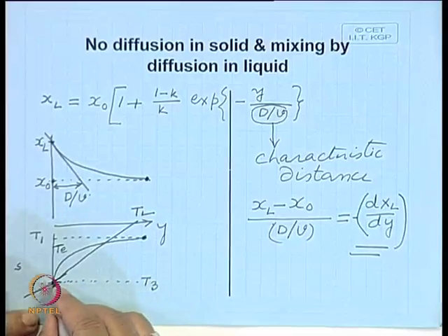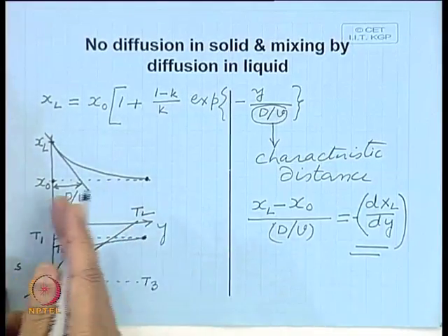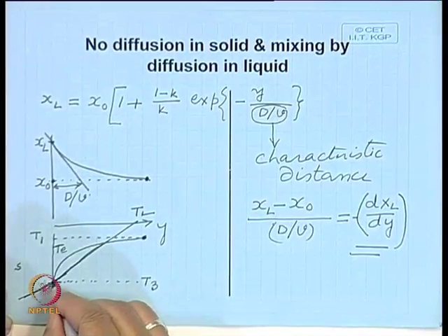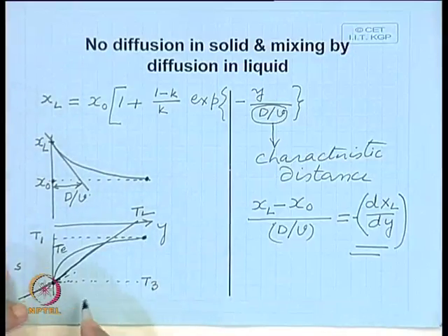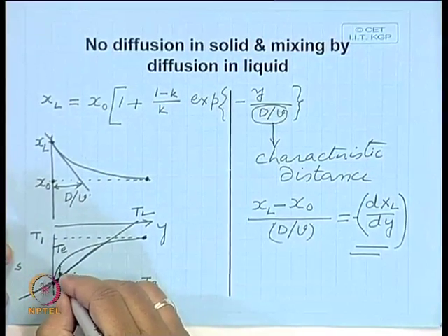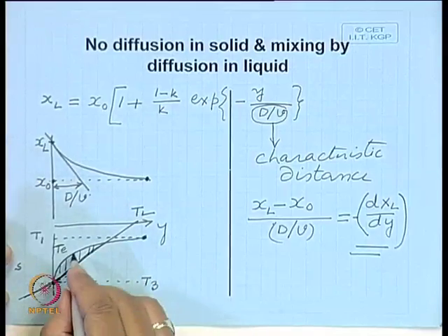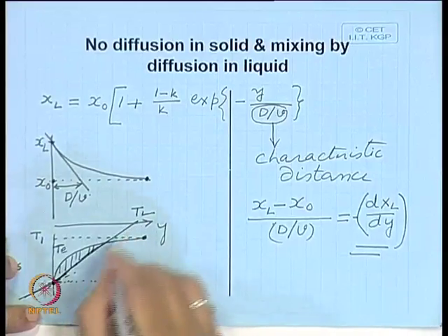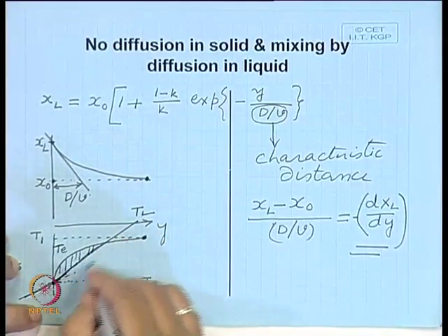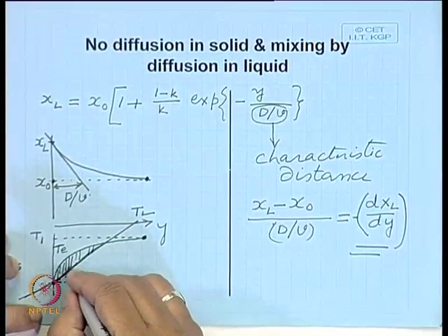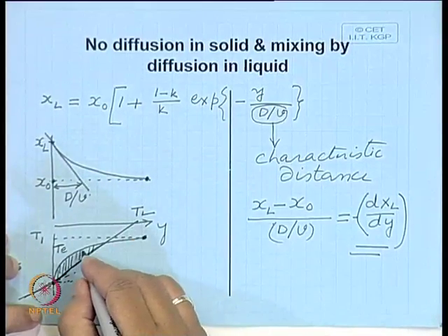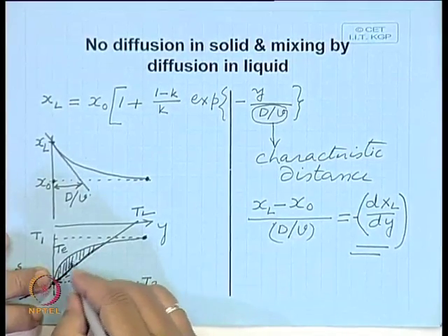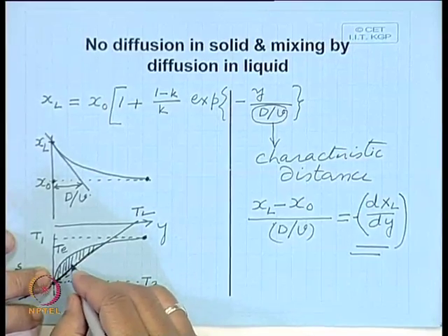So, we maintain a temperature gradient in the liquid. As you move in the mold, the temperature is higher, and this is the solid temperature. Now, in that case we have a region here where there is supercooling. So, even though the gradient is positive, refer back to the pure metal situation. Unlike that, here even though you have a positive temperature gradient, there is supercooling. So, here you can say that this is where your planar front will be unstable.